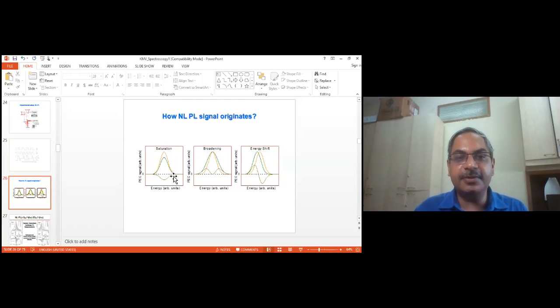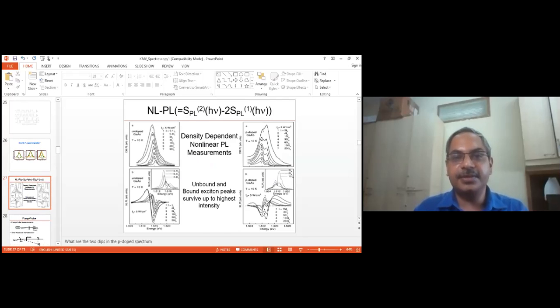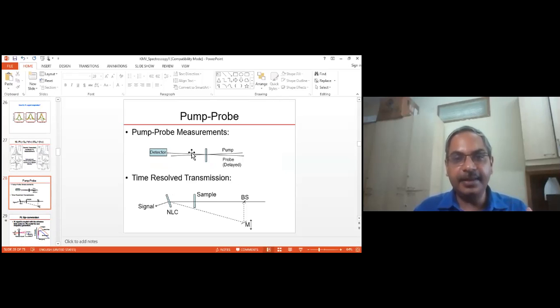So the signal of the nonlinear photoluminescence comes as either a negative, or a double dip, or a positive and a negative kind of thing. Depending on the shape of these signals, we can find out what mechanism is happening in your sample. So we can use this for real measurements. The one thing I mentioned initially is a pump probe measurement.